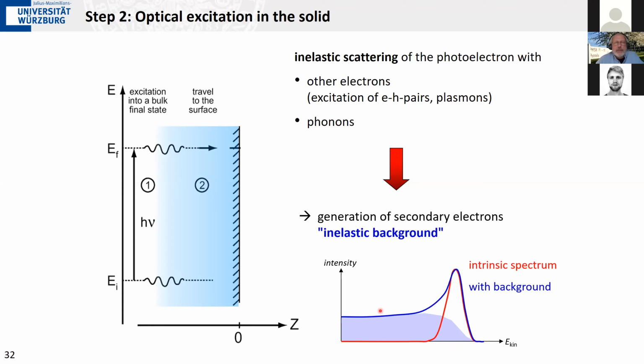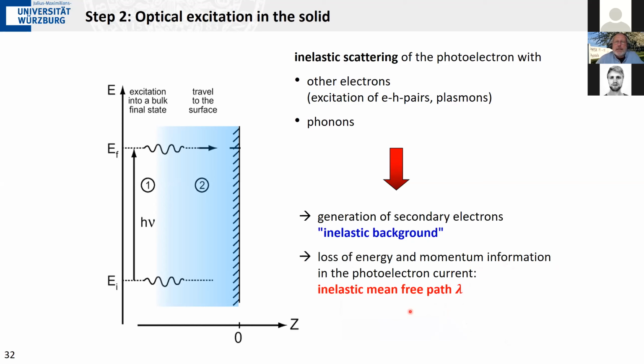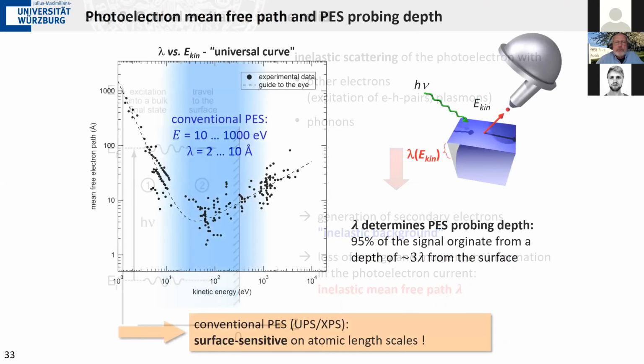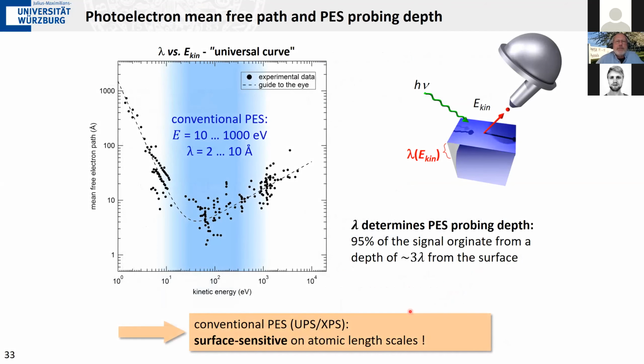as a background that you have to take into account when you want to do any quantitative analysis of intensities. For example, you have to be aware that some of your intensity here is due to the secondaries and it's not intrinsic spectral information. A second consequence of this is that the photoelectrons, the actual ones, still carrying the original energy information, will have only a certain mean free path. I addressed this before, and this gives rise to this inelastic mean free path that we had discussed. This is this mean free path as function of photon energy, this universal curve that restricts our probing depth to about 3 times the mean free path from the surface.